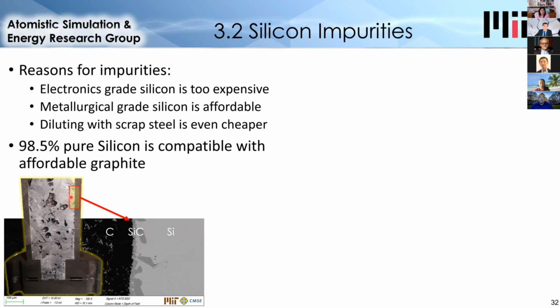And what we found is that the impurities did not cause any problems. The main impurities are iron, calcium, and aluminum. And so calcium mostly evaporates, the iron remains suspended, and so does the aluminum. And so these did not inhibit the formation of a silicon carbide layer. And in fact, we also wanted to investigate, as I mentioned in the economic section, the effect of adding iron to reduce the cost even further.